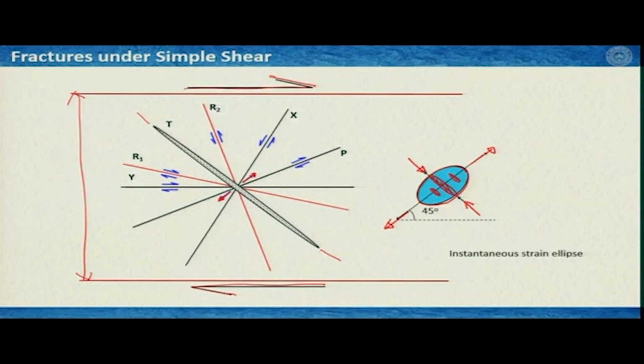One set of fractures you can expect is parallel to the bulk shear direction, and these are known as Y shear fractures. The sense of displacement in the Y shear fracture is synthetic. That means the sense of shear is very similar to that of the bulk shear. Then you form a very low angle shear which is marked by this red line, and this is known as R1 or low angle Riedel shear fracture. This angle is typically 10 to 20 degrees and classically 15 degrees. The sense of shear is also synthetic. That means the displacement along this shear fracture is very similar to that of the bulk shear.